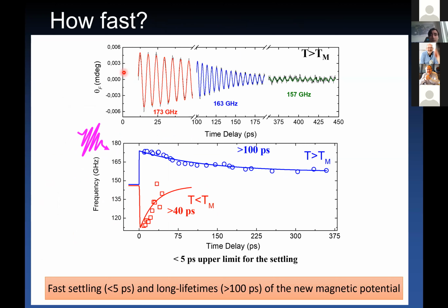We can also measure how fast these changes in magnetic potential are activated and relaxed. We can set an upper limit of a few picoseconds for the settling of this new magnetic potential, and up to hundreds of picoseconds for the relaxation of the magnetic potential to occur.